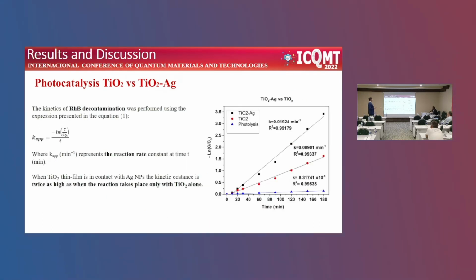Well, we study, of course, the kinetics of these types of decontamination, and as you can see, photolysis, only the pollutant with the lamp, doesn't affect the photodegradation of the pollutant. In comparison with only the titanium oxide, and with the silver nanoparticles with titanium oxide, the difference is clearly the rate constant of the kinetics. The constant of the titanium oxide with silver nanoparticles is too high, twice as high in comparison with the other.